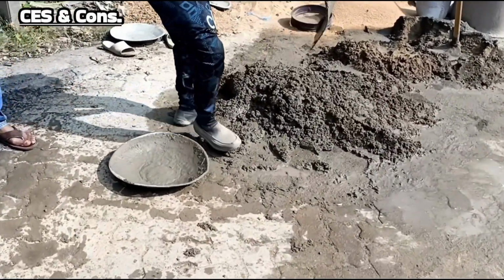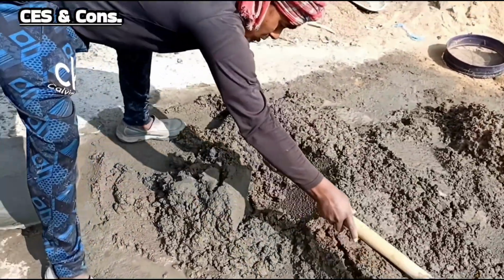Preparation of cement and sand mortar. Cement and sand are mixed dry in required proportions till uniform color is obtained. Water is added gradually, ensuring workable consistency. Mortar should be used within 30 minutes of adding water as per IS recommendations.